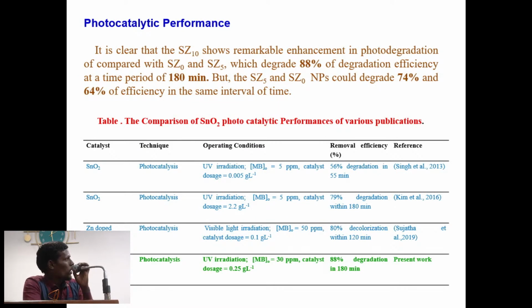The photocatalytic degradation with 10% molar content showed 88% degradation efficiency at the time period of 180 minutes. Then for pure and 5% molar content, 64% and 74%. In the previous work, comparisons of various publications with my work.